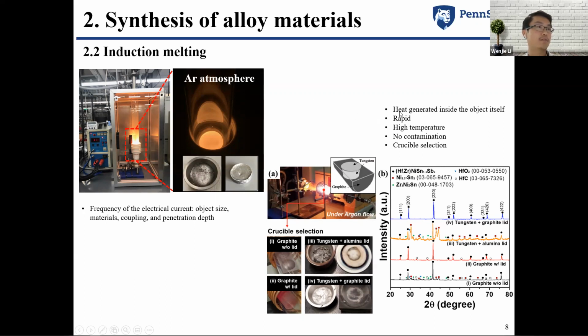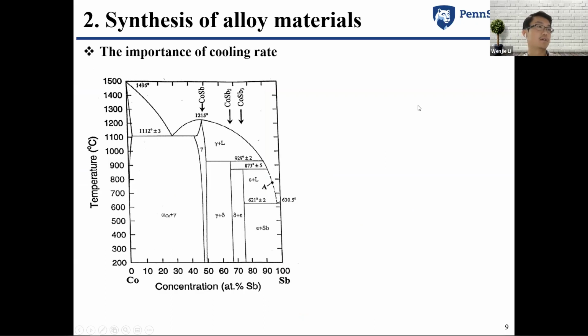So induction melting can provide rapid heating to high temperature. In the lab, induction heating can normally provide a melting temperature of about 2,000 to 3,000 degrees C, and with proper selection of crucibles, we can get rid of contamination and achieve uniform phases. For high-energy ball milling and induction melting, we normally just let the material cool down naturally, but for some alloy materials, we want to maintain phases that only exist at high temperature.